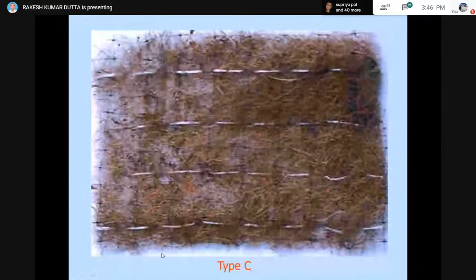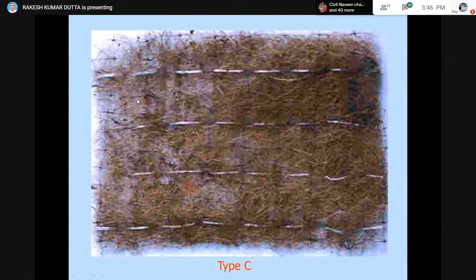So this is the type C material, where it is all a loose bed. Stitching is provided with jute yarn along the direction of the road. This is a small sample just taken out from the main roll for the photograph. Now you can see the unevenness also. At some locations you are able to see through to the other side, whereas at some locations the web is thicker and at others the web is thinner. At some locations it is not possible to see through, right? Because of this, you get variation in the strength of these products.